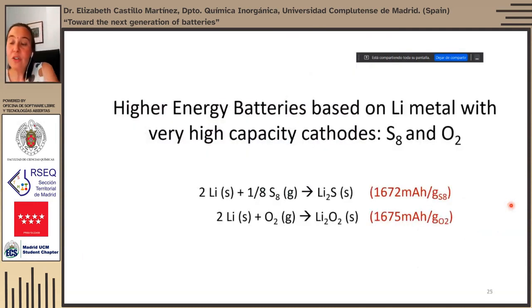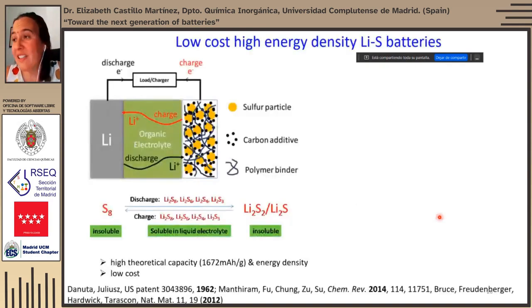So if we could use lithium metal with some of these polymeric, ceramic, or glassy electrolytes, what would be the best cathode material? Although we've seen many inorganic oxides, polyanionic compounds, phosphates and sulfides as electrodes, actually, in terms of capacity, we could even beat them with elemental sulfur and elemental oxygen. And that's what actually has been made. Their specific capacities for the formation of lithium sulfide and lithium peroxide are very large, more than 1,500 milliamp hours per gram. This is almost 10 times that of the largest capacity cathode material. But of course, these batteries also have some problems.